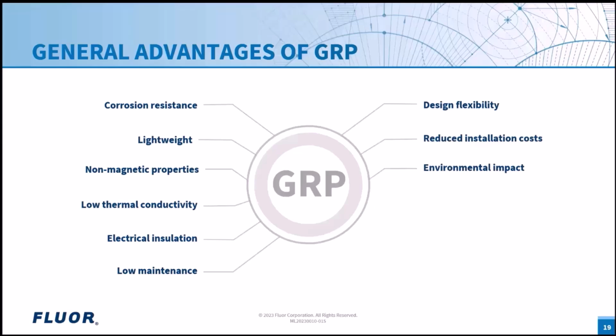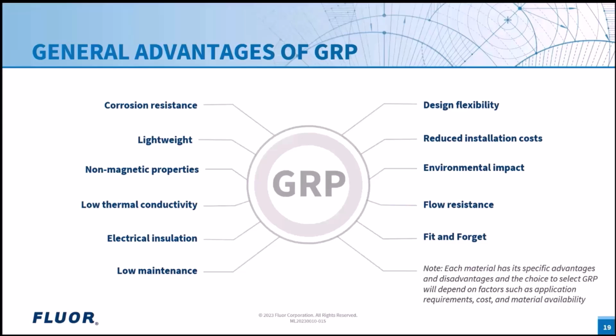Also, GRP materials have a lower environmental impact compared to steel, as they require less energy to produce and have a longer service life. While the flow resistance of the pipe is typically close to that of steel when the pipeline starts its operational life, due to corrosion effects, the flow resistance increases for steel piping, while it stays unchanged for GRP. Although there's more effort to be spent during the design process and during installation, there's more supervision, more critical reviewing of engineering documentation, it will give you less effort once installed. Call it fit and forget. It shall be noted that each material has its specific advantages and disadvantages, and the choice to select GRP will depend on factors such as application requirements, costs, and material availability.